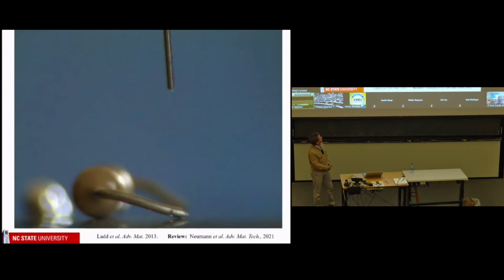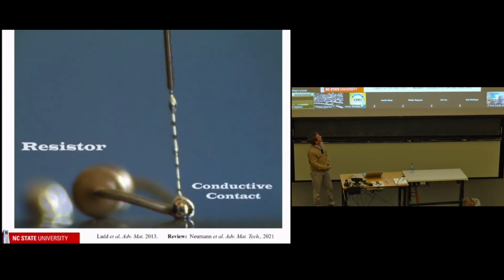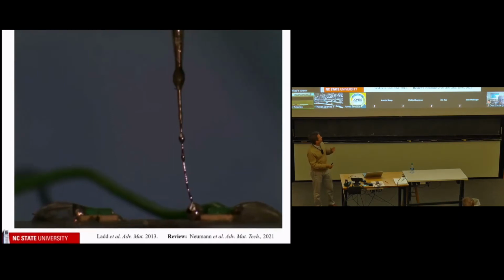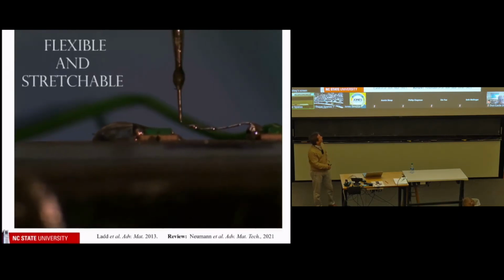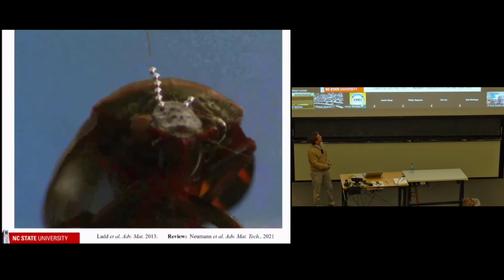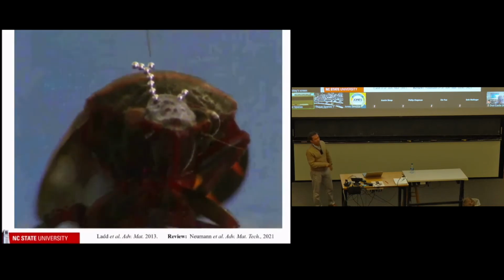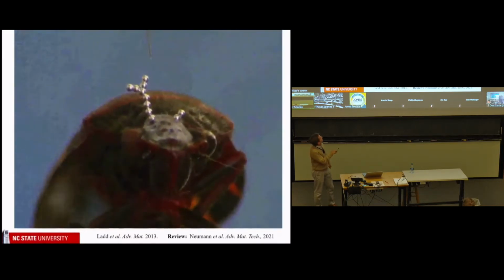Because it's only held together by a 3 nanometer oxide layer. But this layer forms so fast, you can do a burst of pressure, and it will oxidize midair and sort of form its own hose. Like a garden hose, it's liquid on the inside, so you can drag it around, and it's electrically conductive like a metal. And this is about as close as we get to biology in my lab. This is a dead bug.